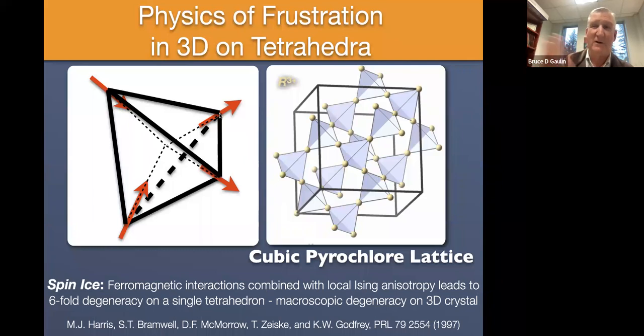So the moments couldn't line up. They couldn't be either parallel or anti-parallel, even if they wanted to. And actually, in this model, they do want to be parallel. There are ferromagnetic interactions between the moments. So they would really like to minimize their exchange interaction by aligning parallel, but they can't align parallel because their easy axes are non-collinear. So this is close to a ferromagnet, but it's not quite a ferromagnet.